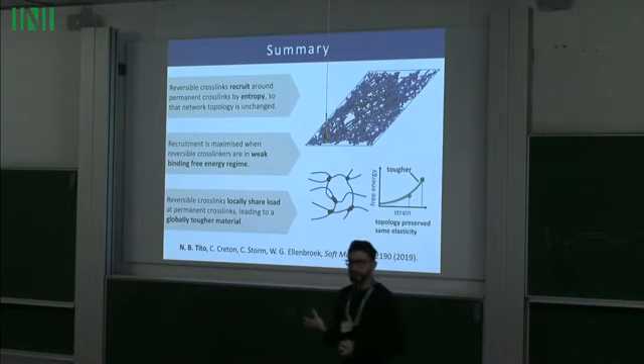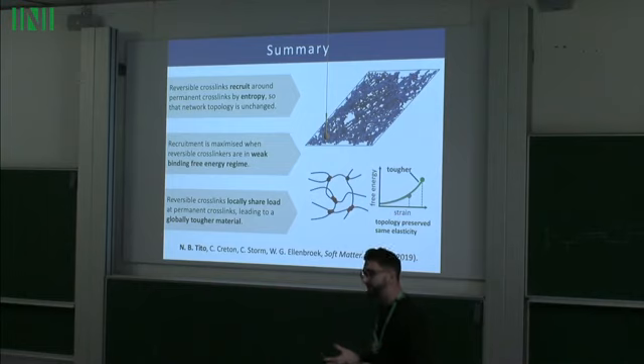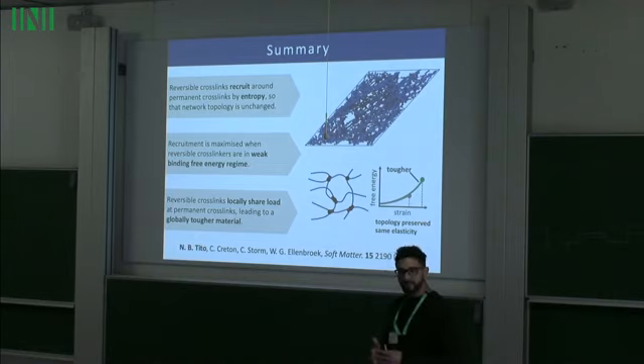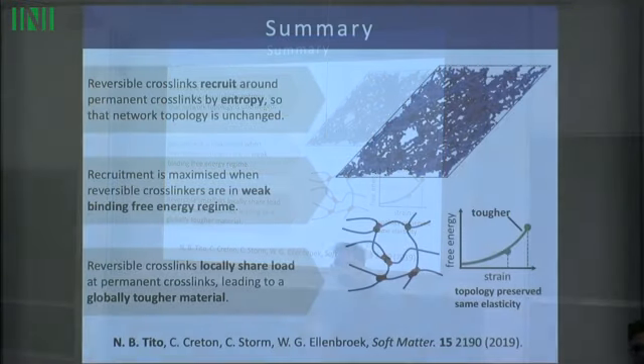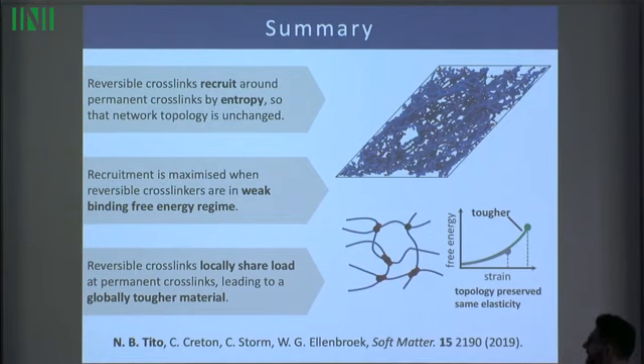And just to summarize, this was a story about how entropy drives reversible crosslinks to recruit around permanent crosslinks. Paradoxically, perhaps, it's a situation where entropy leads the linkers to exhibit some visible form of order. They're not disordered, actually. It leads the polymers to have the most possibilities at the molecular scale, and that's why they're doing that. The recruitment effect is maximized in this weak binding free energy regime. And once these linkers recruit, they share load at the local scale, and that's what leads the material to be tougher on a global scale.